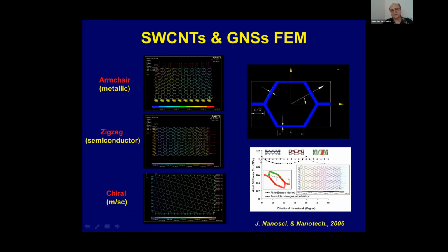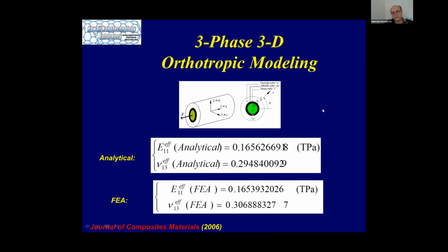So in the analytical solution, we get 1 terapascal for modulus, which is this line. But in the finite element, depending on chirality, when you have pulling on a zigzag, you get slightly higher, and then you come to armchair, and then you repeat because it's a 30 degrees repeatability. See, this is hexagonal, so every 30 degrees it is periodic, it goes back. So it oscillates around that 1 terapascal. So we had a very close approximation between the analytical solution and finite element.